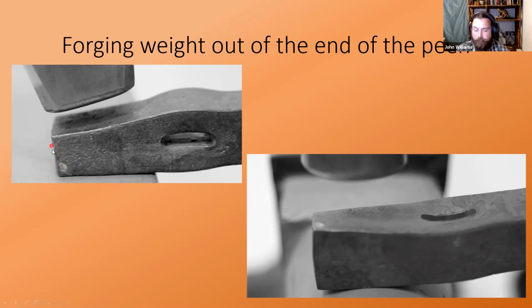And the business end of this face of the hammer, the peen of the hammer, will be 1 inch wide by 3/8 of an inch thick. So I know that it's going to be 1 inch by 3/8. And if you know good forging practice, you don't want to try to forge rectangular bar stock on edge the hard way. If it's outside of a 3-to-1 ratio, it tends to do what I call curtaining, where it will sort of collapse and do an S curve on you, or it'll mushroom. Oftentimes it'll mushroom on both faces and create an hourglass cross section. So if you want it to remain good parallel edges and keep pushing that stock towards the center without a lot of stock distortion, you stay at that 3-to-1 ratio.